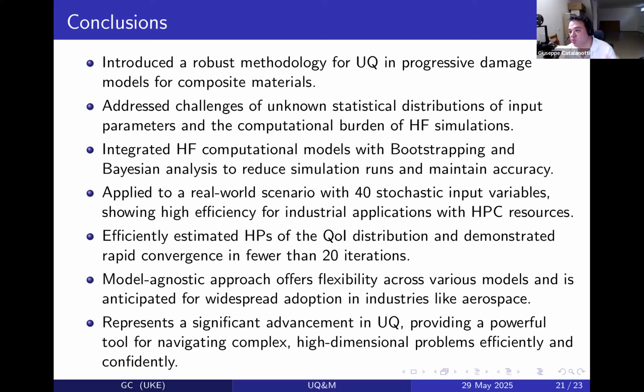Or you can also combine this approach with approaches based on the Fisher information matrix. So there are, in my opinion, approaches that will allow you to get details. It's a problem because sometimes you get, on the same material, experiments that I've seen myself, because for some years I worked in industry, strengths, something very simple, coming from one plant or from another plant, and they're totally different. So the data that you get are heterogeneous, but this is something that can be worked on in the statistical model, taking into account these details, but also on the actual testing, because you might improve experimental protocols to avoid that. So it's not just statistics, or just computational modeling, it's also experimental protocols.